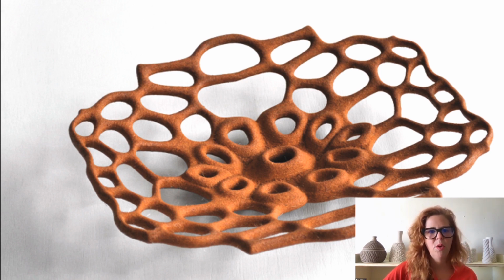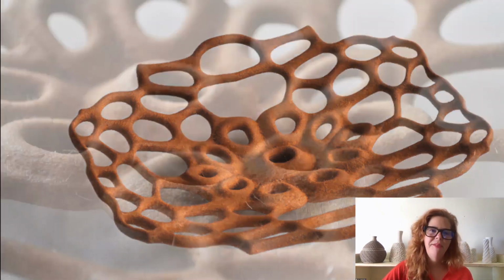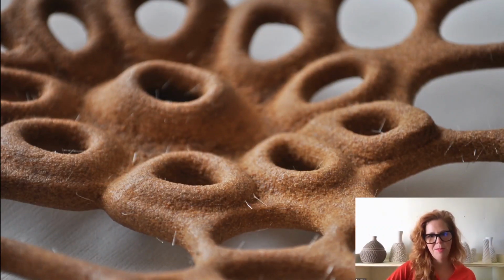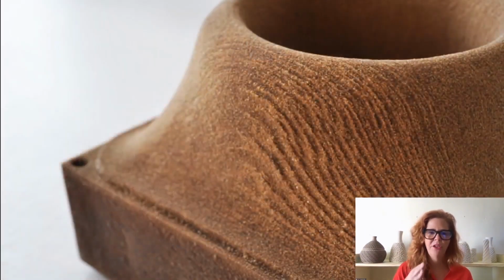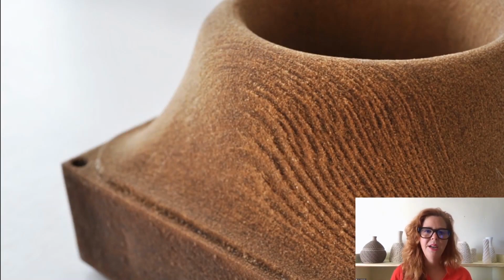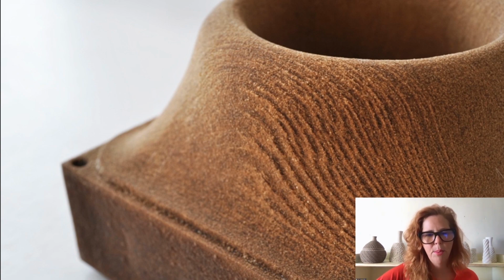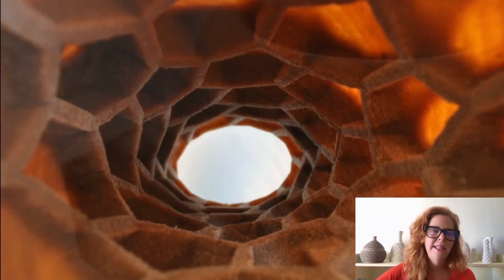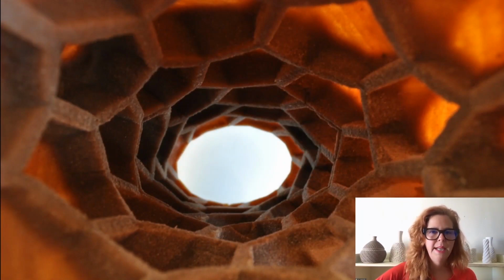And we've developed a formula that takes advantage of fibers to give increased tensile strength. And one of my favorite things about 3D printing with sawdust is that we're able to create a kind of artificial grain in the wood, depending on the orientation of the digital model within the print bed itself. And when printed thinly enough, the wood can be translucent.